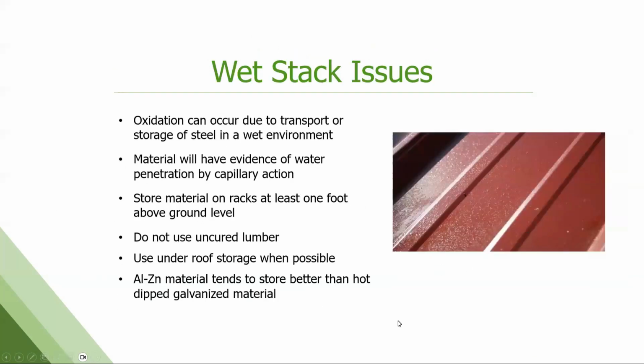This is the wet stack I was talking about, or storage corrosion that occurs. Can happen during transport, during storage. You can get moisture due to sweating. You can get moisture due to actually rain or precipitation in between the stacks of panels. There's no good airflow. It's a chemical reaction that takes place underneath the paint, starts to push that paint off. You get these little tiny, like micro blisters almost. It kind of feels rough.